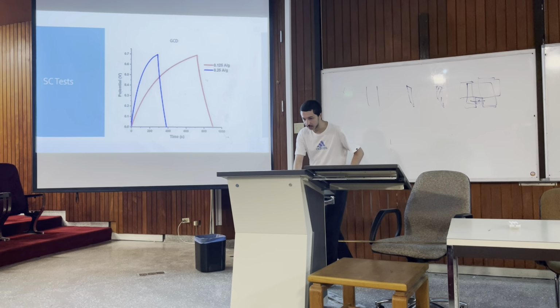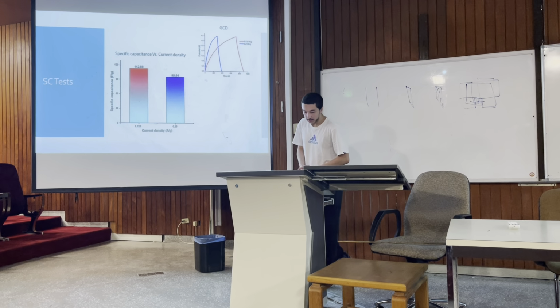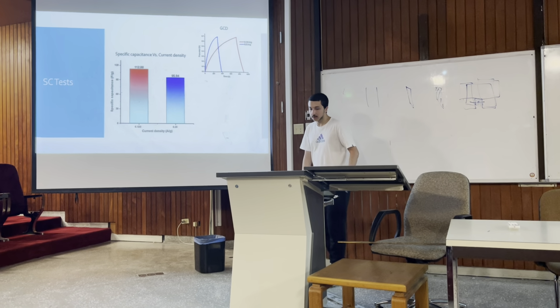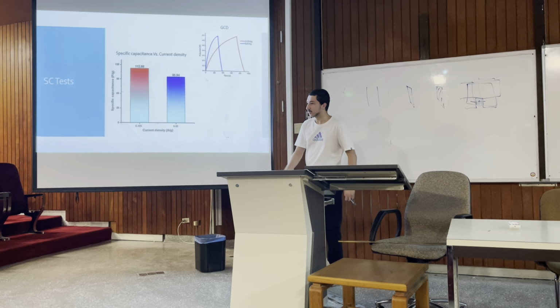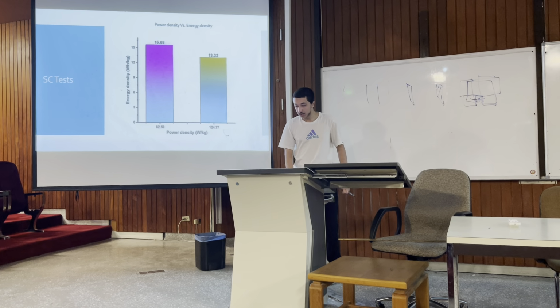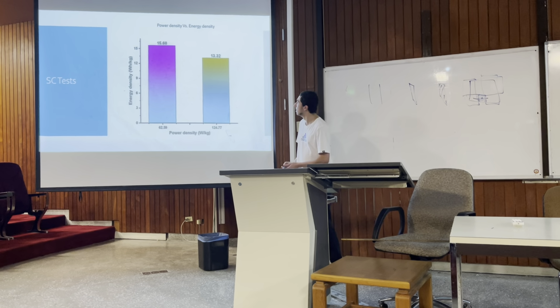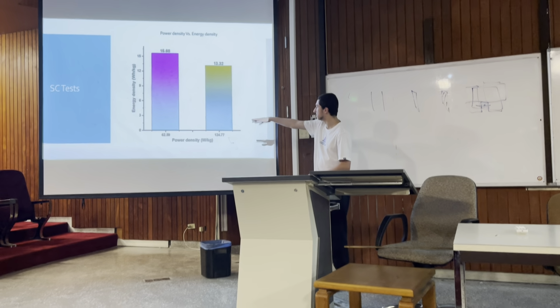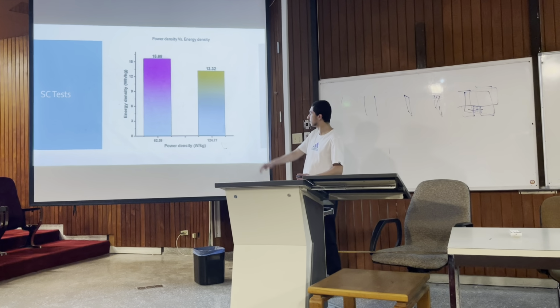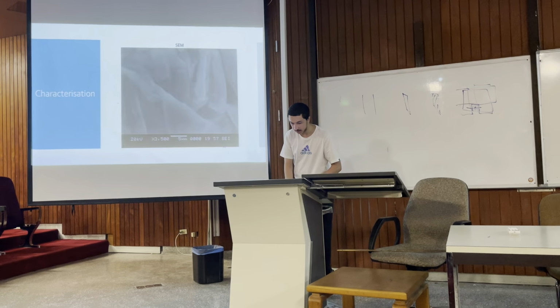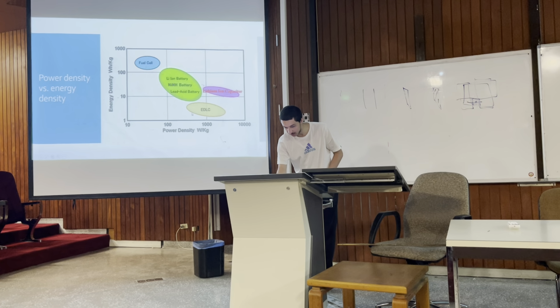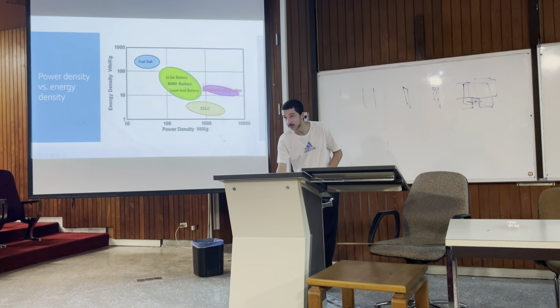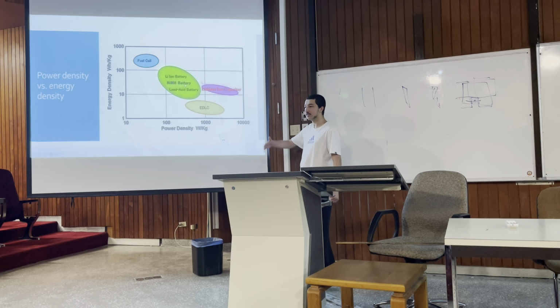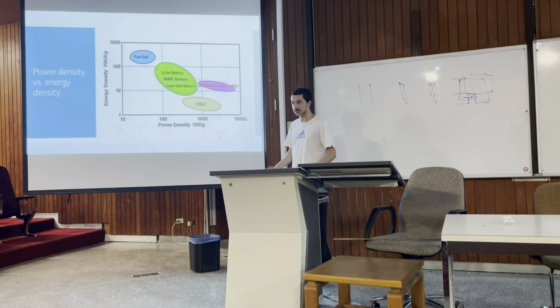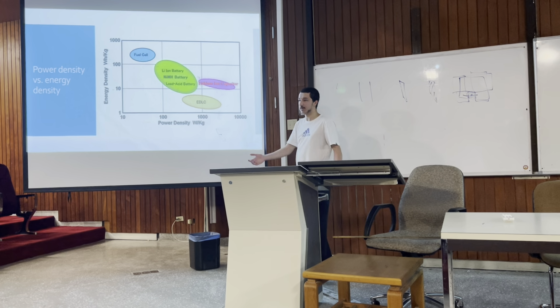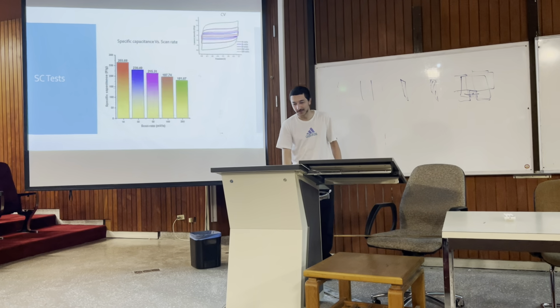Again, nothing significant here, but when we go to here, this is when we get some meaningful results. Again, relatively large capacitance. Also, I found this very interesting: the power density we got almost 60 to 15, or 120 to 13. So it's actually pretty efficient. It didn't give us as much power output, but we got pretty good storage, comparable to a typical battery, which I found very interesting, alhamdulillah.